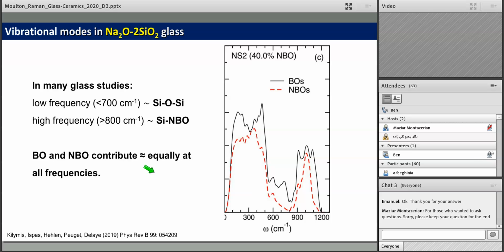In a simulation study of sodium disilicate glass, Kilimis et al. simulated the vibrational modes based on some assumptions. And if you read some of the older glass literature, they usually equate all of the low frequency modes with Si bending, and therefore these modes are related to bridging oxygens between two silicon tetrahedra. And this is separate from the high frequency region above 800, where the vibrational modes come from silicon NBO vibrations. This is the standard picture, and the reason it was thought that NBOs are important is because they're only bound to one silicon. They're not bound to another silicon covalently on the other side, so they're free to vibrate more strongly, and it was thought that they were more polarizable.